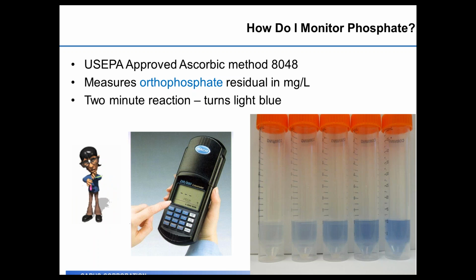This test is relatively easy to run, and you can run it when you collect free chlorine samples out in the distribution system, or chloramines. Just collect more sample and then run this as a separate test so that you have data on what the orthophosphate levels are out in the distribution system.